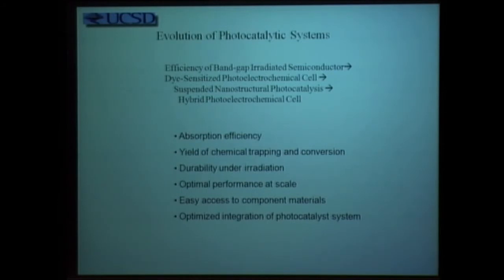We moved on to dye sensitization, one where the dye itself is absorbed rather than exciting the solid support. Our third approach is to think about the same experiment in which we've minimized the size of the titanium dioxide species. We have, if you will, with that initial electrolysis experiment, taken one metal and the other titanium dioxide and miniaturized them so the wire connecting the two particles has gone to zero. As the two particles go to zero, they come into contact, and that contact allows you to have different parameters for the operation of the system. Absorption efficiency will be different, the yield of chemical reactions, and so forth. These also provide ways in which two catalysts can come together to do this kind of enhanced reactivity.